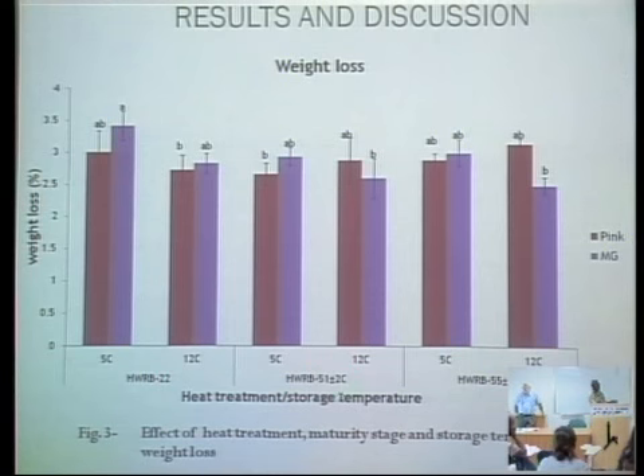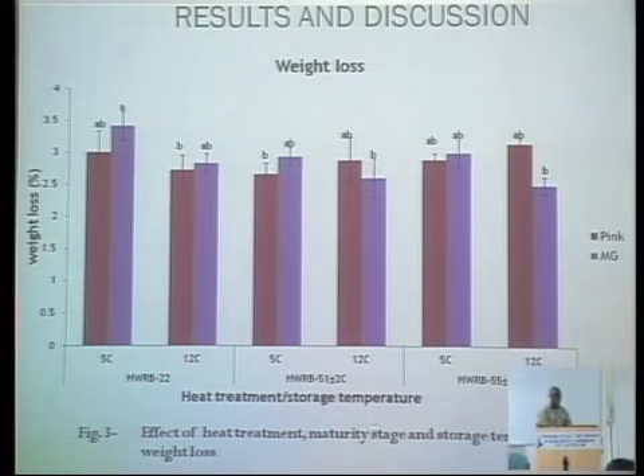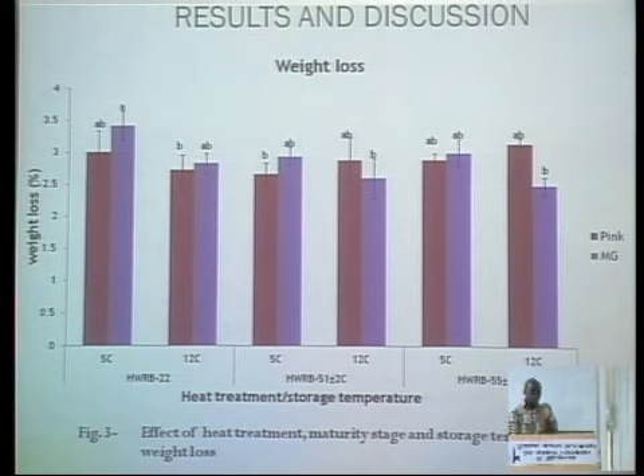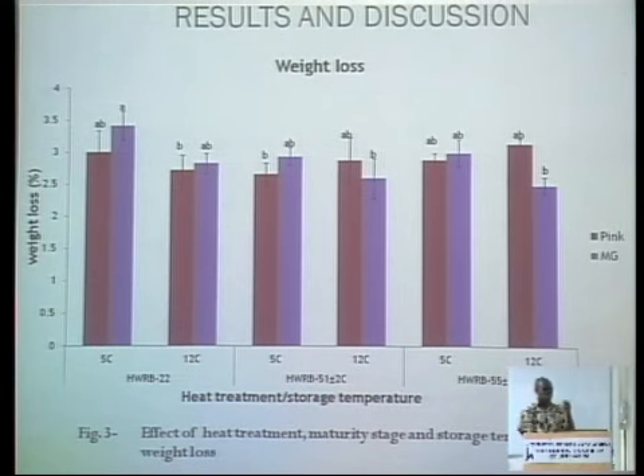let me start with the heat treatment at 51 and at 55. When you wash the fruit at 55, if you take a microscopic image of the peel of the fruit, you see some layer of wax around the peel. So this wax at this temperature was able to seal the visible openings on the peel. So that would have accounted for some reduction in weight loss in this heat treatment. But of course here, there wasn't any crystallization of the wax around the peel.